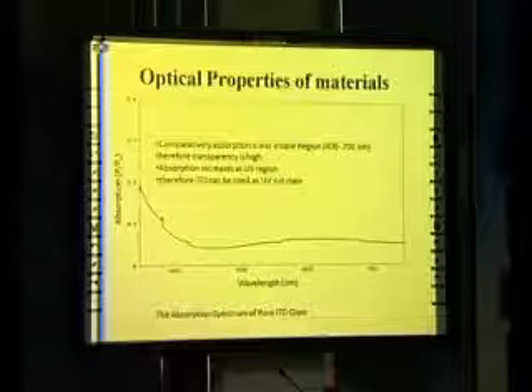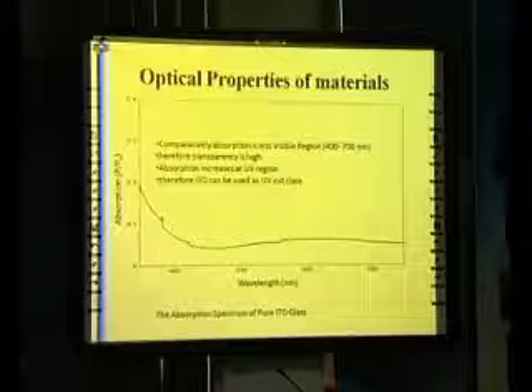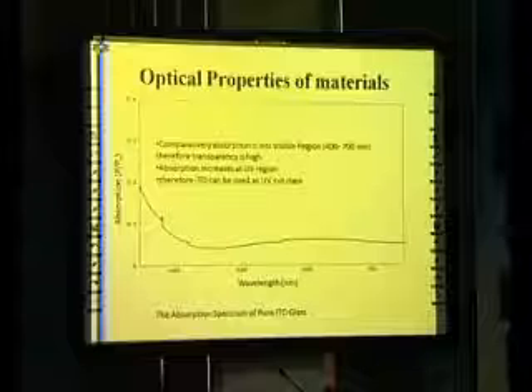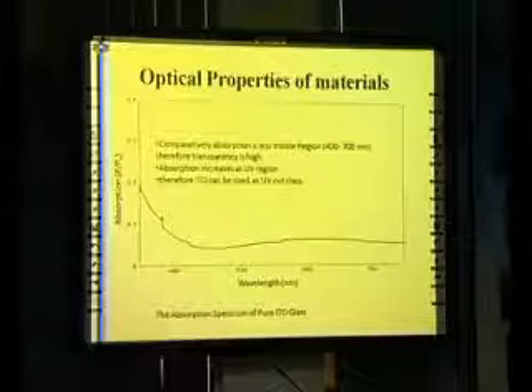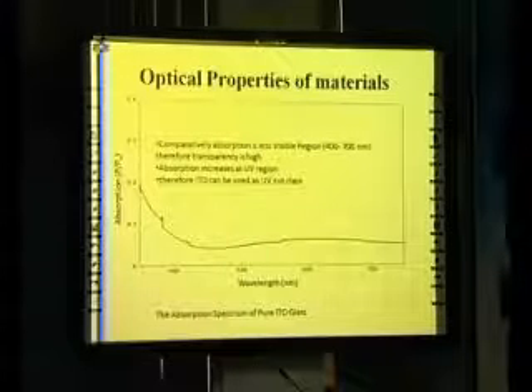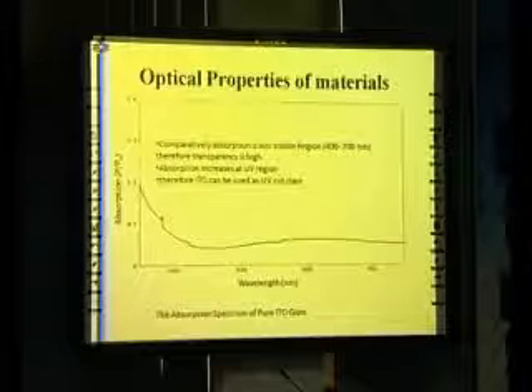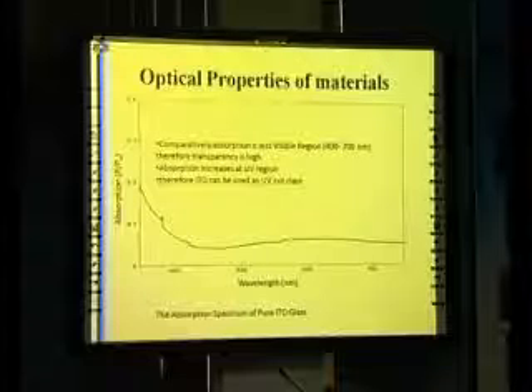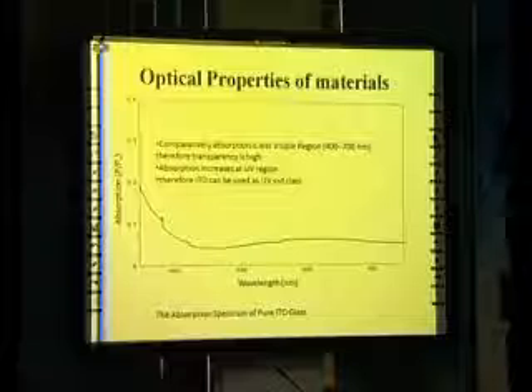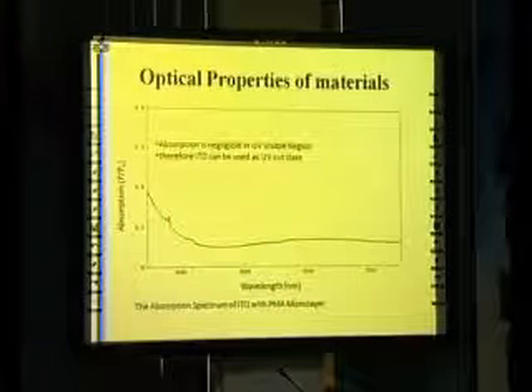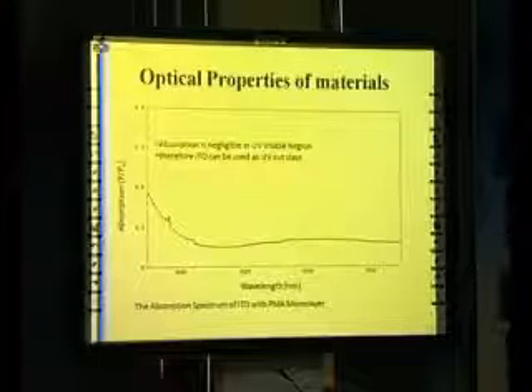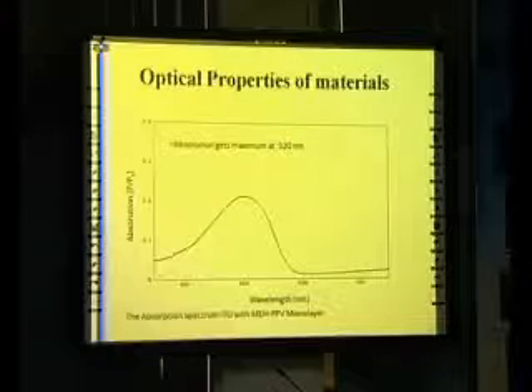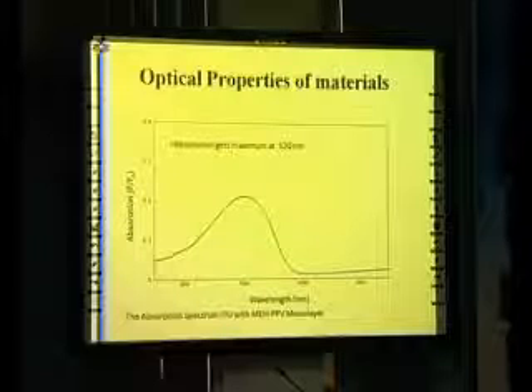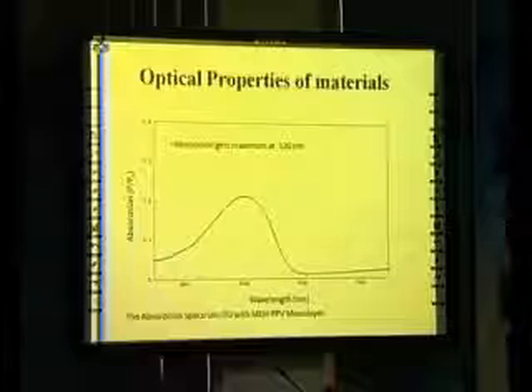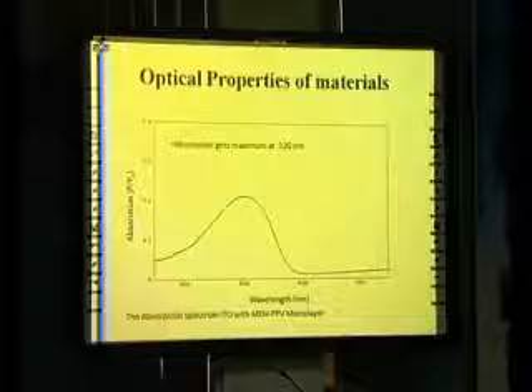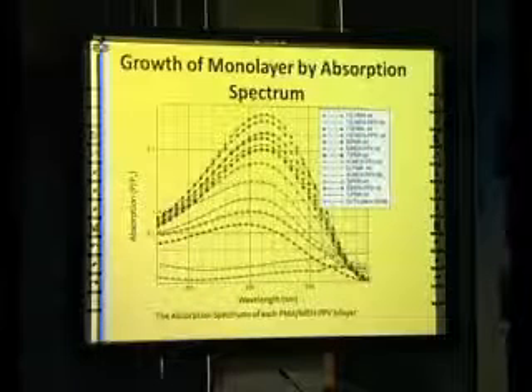Now if we take the optical properties of the material being used, this is only when using ITO glass without adding any layers. So this is the characteristic. You can see wavelength and different colors of light, the visible range. So comparatively absorption is less in the visible, and absorption increases in the UV region. Anyway, after adding layers, this is after adding one layer, the PMA layer, but we need another layer to see the difference. Right? So you can see at this wavelength, 530 nanometers, we get the maximum absorption. So that's the range this cell can use to get maximum energy.